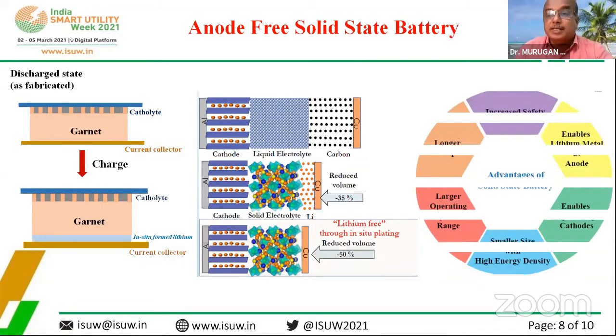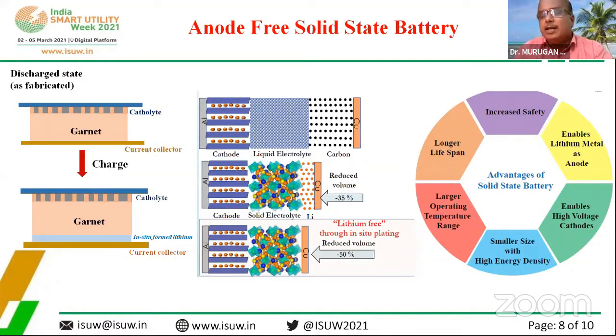Initially, you can reduce and you can have these complete metallic lithium metal solid state batteries. So the advantage is increased safety because we have a perfect ceramic layer, which enables lithium metal as anode. So you can think about the high voltage and smaller size, which means high energy density, and operating temperature, because particularly in a country like India, with tropical conditions, it should stand at least 45 to 50. And this technology is a mature technology because it's nothing but a 2-layer. So technology-wise, you can reduce the cost and the lifespan is also expected to be much more compared to conventional lithium-ion batteries.